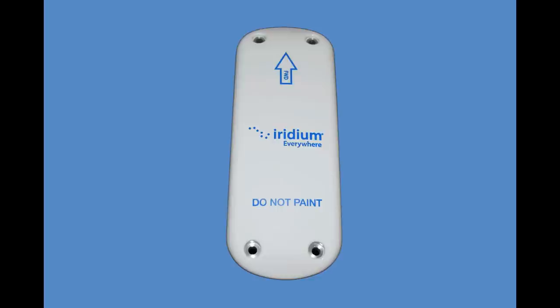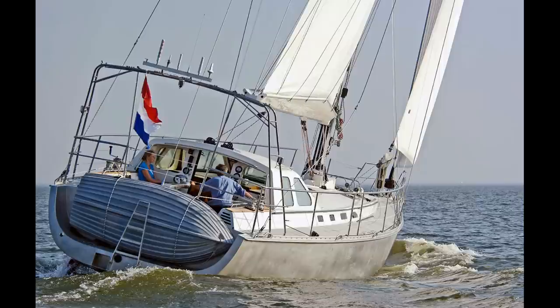I was watching an interview with an aluminum sailboat owner who was simply moving his iridium antenna — the satellite internet antenna you'd have on an offshore cruising boat — from low on the stern rail up onto his arch. In doing so, he inadvertently introduced stray currents into the hull. As a prudent aluminum sailboat owner he had an electrical meter permanently set up to test the hull for stray currents at all times, noticed the problem immediately, traced it back, and corrected it before it harmed his boat.